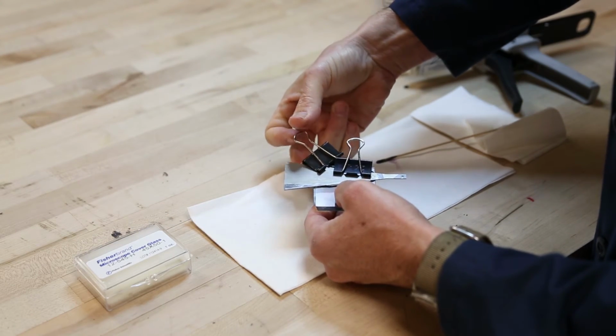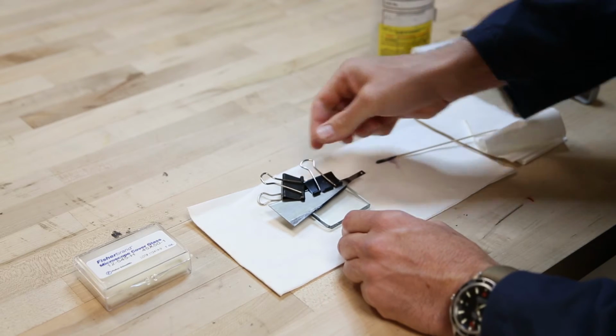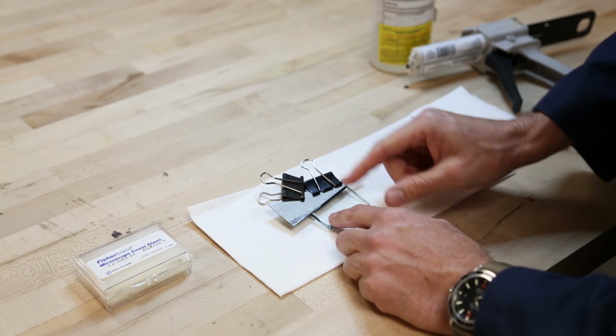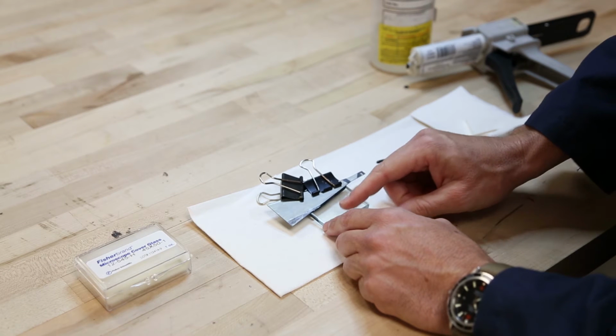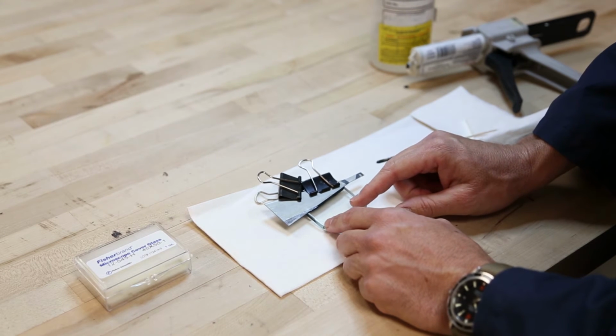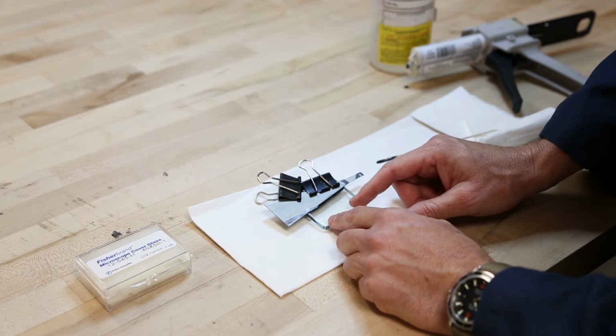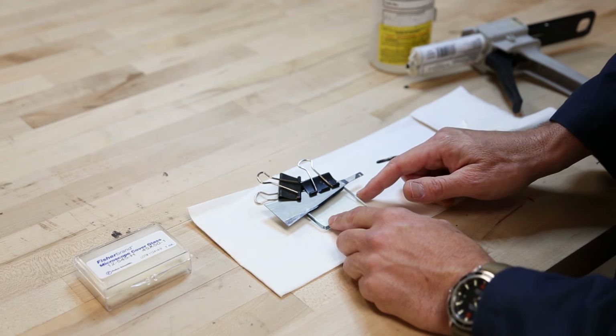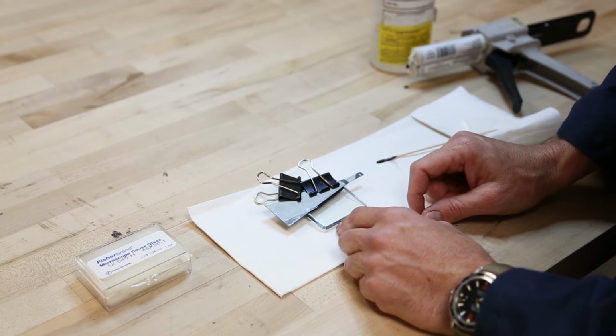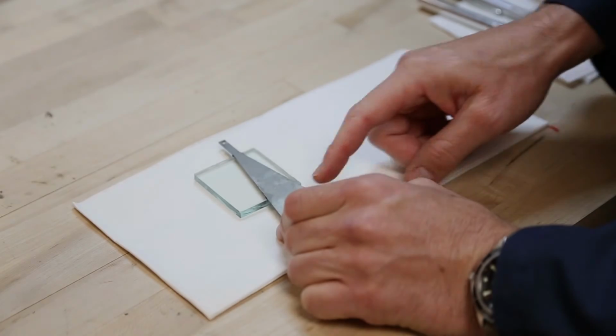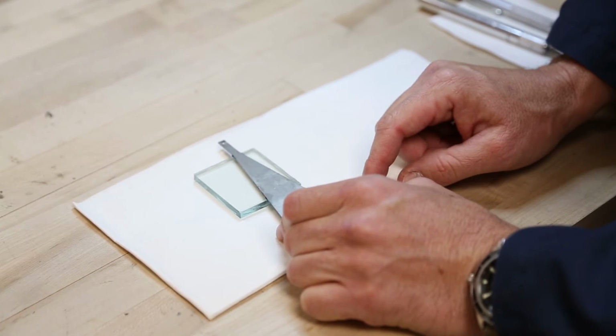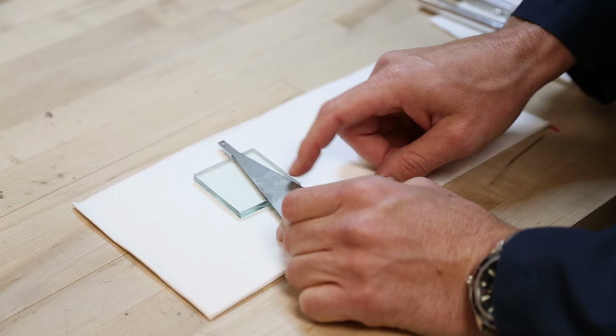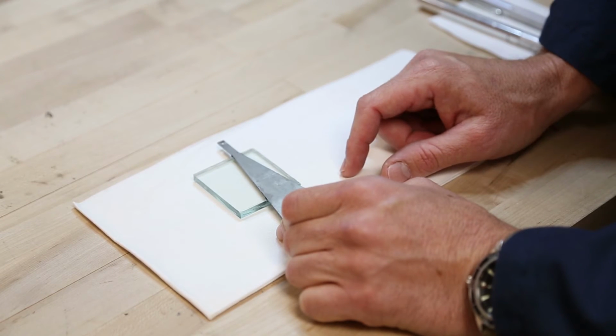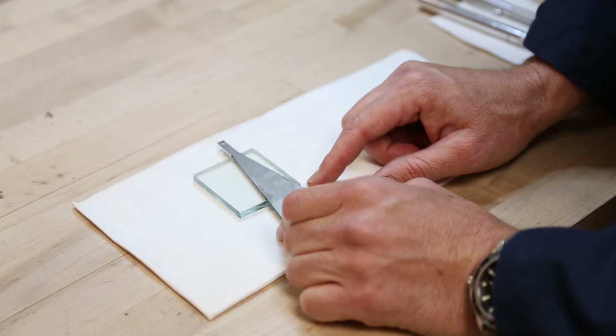For this DP 420 epoxy, the oven can be closer to 80 degrees for its elevated temperature cure. And after it's been in there for just 5 or 10 minutes, I'll take it out, remove any excess that has squeezed out, and then put it back in the oven for an overnight cure. The epoxy is fully cured on this sample. I went ahead and removed any excess that had squeezed out, and we're ready to prepare it for testing.